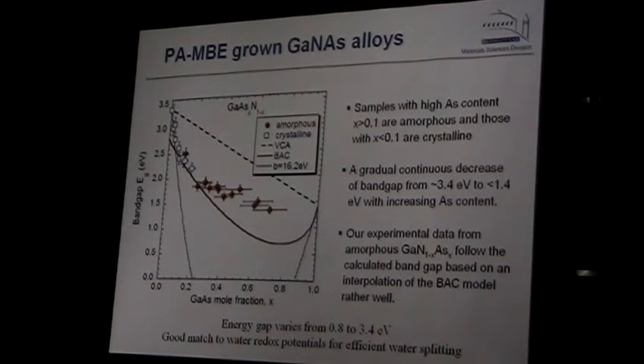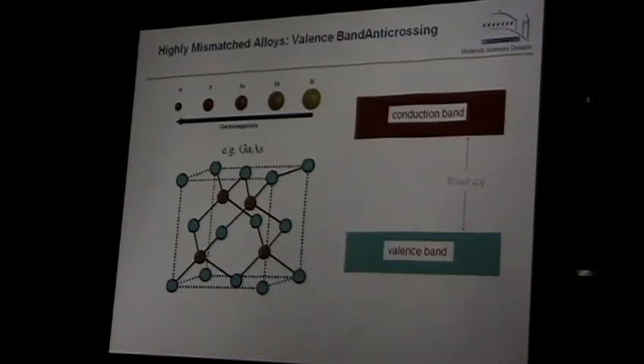What happens is when you take this amorphous material and start to anneal it, you see phase separation. So we see nanodots of gallium arsenide in a gallium nitride matrix or something like that. And this seems to be very self-organized in some kind of superlattice. So this is a potentially interesting aspect, but it will require much more study.